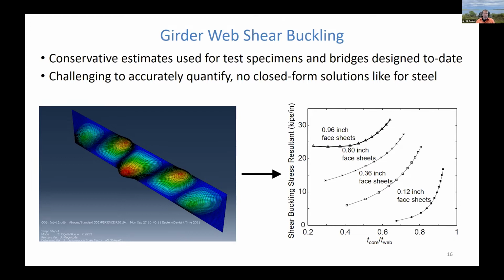The reason we choose an aspect ratio of about 5:1 is that as it gets larger, the buckling capacity doesn't really drop much after that. And it actually is a high aspect ratio because, unlike a steel girder, which is also very much subject to web buckling, we can't put stiffeners in there. We can't develop tension field action. We can't build panels into this. It really is an unstiffened web.